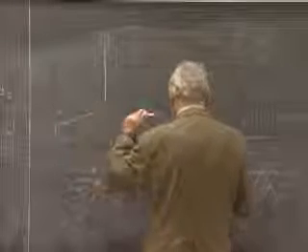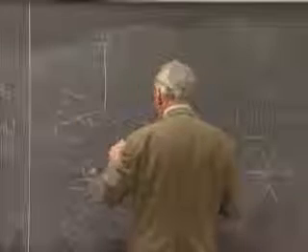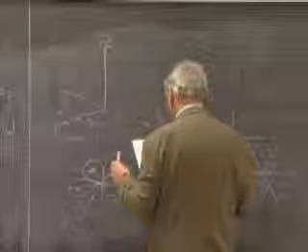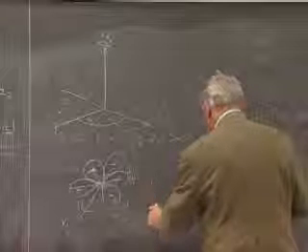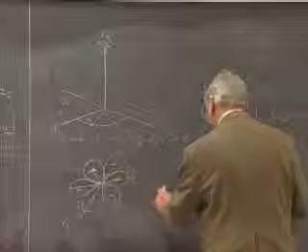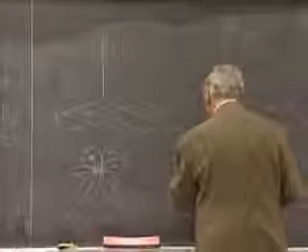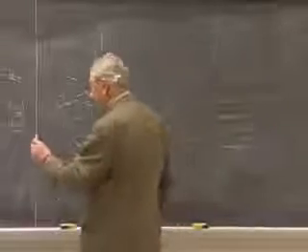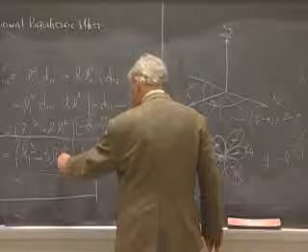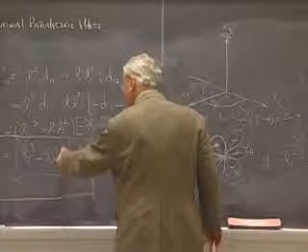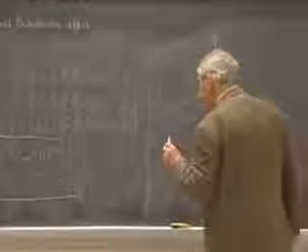Okay, call this angle phi. In the x1, x3 plane, d111 prime turns out to be L1 cubed d11. Before you look at our general expression, L2 is cosine of 90, so this thing drops out. We're left with simply d11 prime equals L1 cubed times d11.